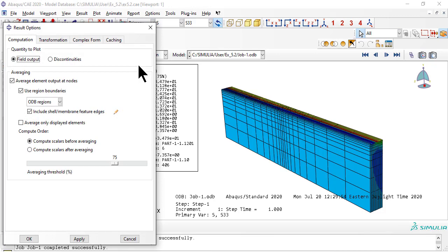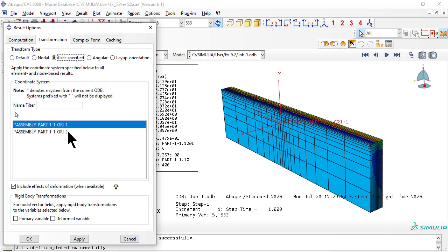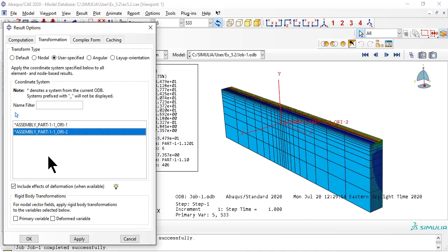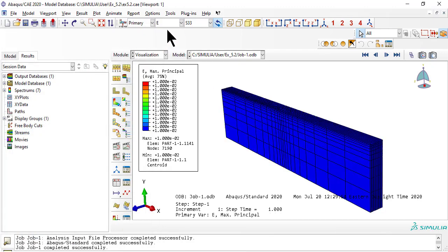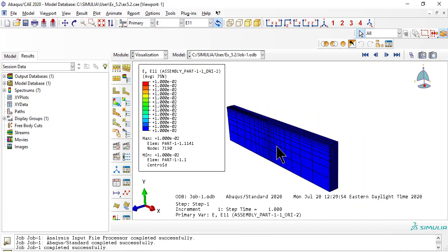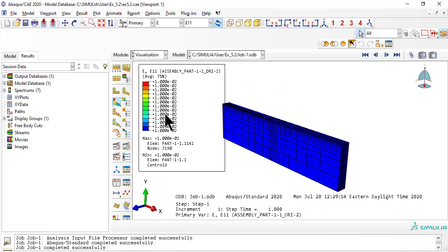If we want stress and strain tensors in global coordinates x, y, z, we have to apply a transformation to the results. We transform to the coordinate system of lamina number 2, the zero lamina, which is already aligned with the global coordinates. You can see that now E11 is uniform everywhere and equal to the applied strain. In fact, E11 is actually the global strain EXX, but you have to know that from context.